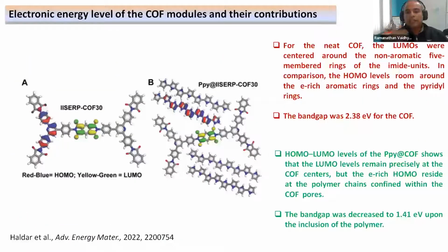So we then did a quick computational modeling, and then we tried to see what is happening at the electronic level in this material. So here is the HOMO-LUMO states of the COF, and you can see the LUMO is residing at the imide units, which is non-aromatic, and the HOMO is residing at the rich nitrogen centers of the material. But when I load the polypyrrole, what happens is the LUMO remains the same, but the HOMO is now residing more towards the polypyrrole, which seems to be very electron rich. And this now could be the reason why you are getting very high electronic conductivity and thereby a superior charge storage.